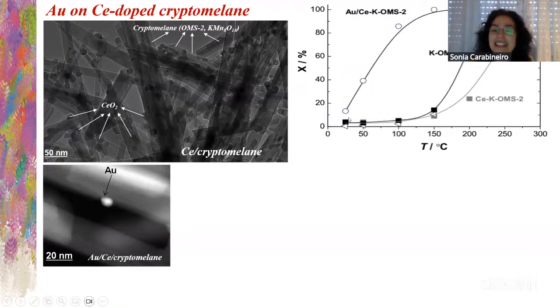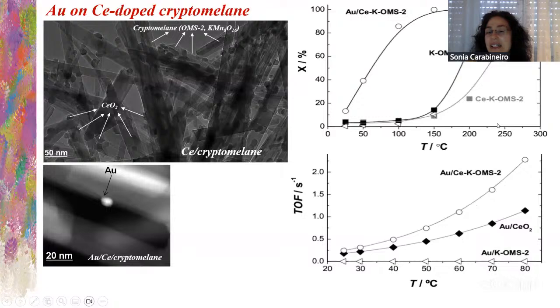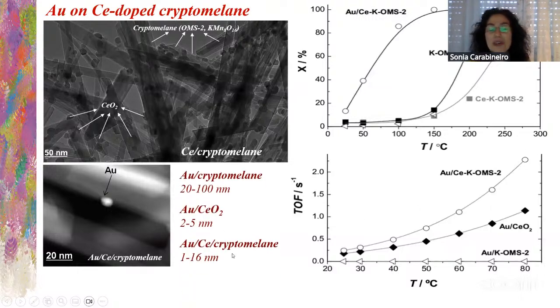That's interesting. So we wondered, okay, maybe cerium oxide is enough and the cryptomelane doesn't do anything. But no, we tested. So gold on cryptomelane, not good. Gold on cerium oxide like that, and on cryptomelane with cerium oxide, it's better. So if we compare the gold size, on cerium oxide it is smaller, but it doesn't matter because it's not so active as it is on cerium cryptomelane.